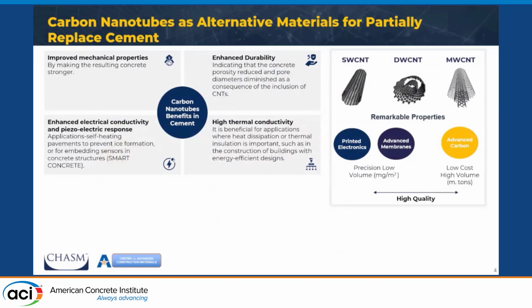Carbon nanotube is an alternative nanomaterial for partially replacing cement, due to its remarkable properties. It has been proven that carbon nanotube improves the mechanical properties of the concrete, enhances the durability, enhances the electrical conductivity and piezoelectric response, and also has high thermal conductivity.